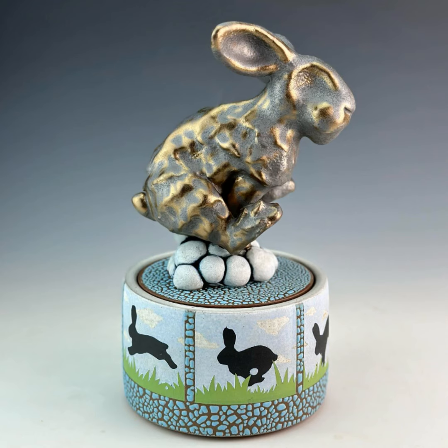And then after that is the glazing, and the reticulated glaze that I use is a bit of a pain in the butt to work with, truth be told. In order to make it really work well, I have to mask off the sections that I don't want to be glazed, and I use an auto body tape because it's got a little bit of stretch to it. So it'll go over curved surfaces and it'll stick really nice because I'm a sucker for nice clean lines. And then I'll wax the handle out. I'll mask off all the decoration and the color that I had done in the last bisque firing, and then I dip it into my reticulated glaze and I put it directly into the kiln, so that I never touch it again.